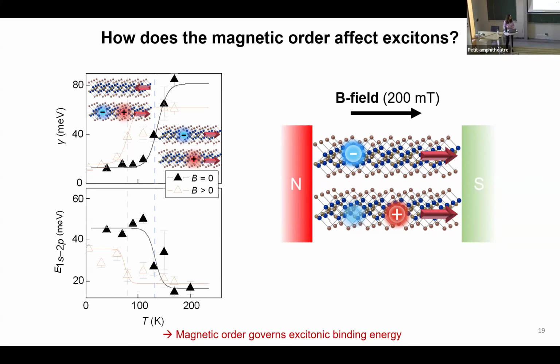Yeah. And at low temperatures, the fact that the energy of the transition changes, is this kind of a Zeeman effect? You mean this? Yes, exactly. Because we start to feel the effect of the magnetic field, even though it is not strong enough to induce a full ferromagnetic state, it can still locally liberate the electrons and holes across the layers and reduce slightly their binding energy.